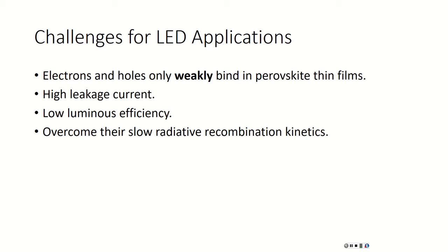Well, in one of the papers that I read, when they tested the luminous efficiency of the perovskite, they ran it against 60 devices, and the champion device, the best efficient device, where the external quantum efficiency was the highest, was 14.3%, but they were getting some that were low, about 12%, 10%. They had a histogram of it, but the highest they found was 14.3%.